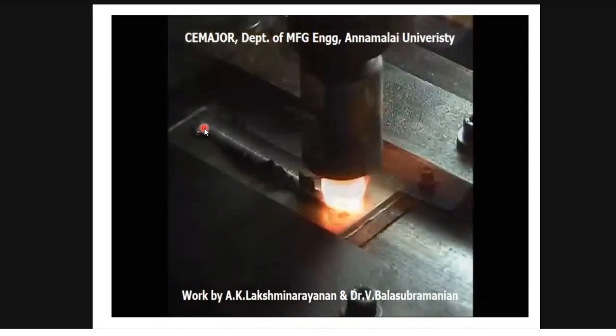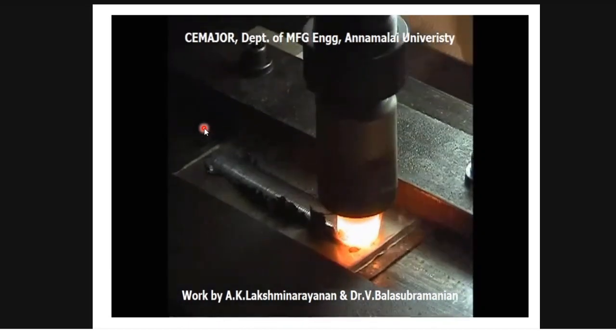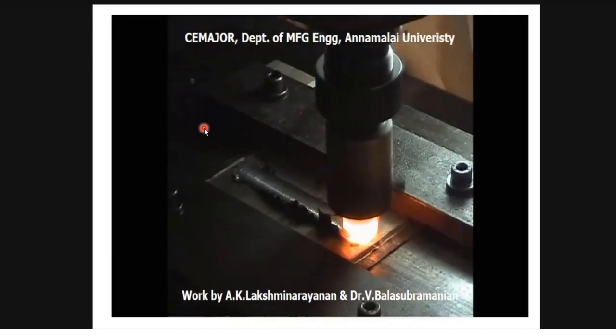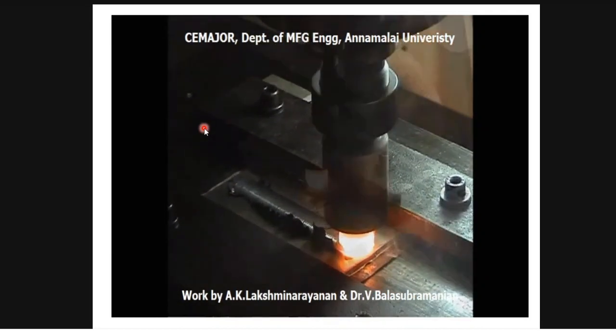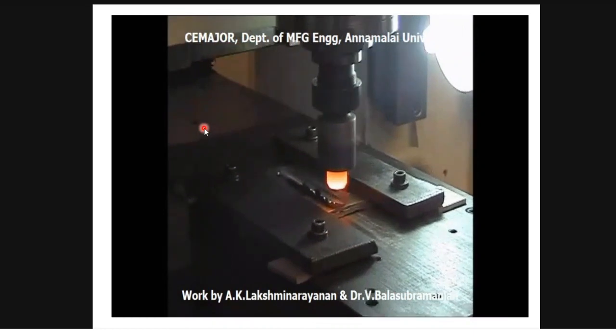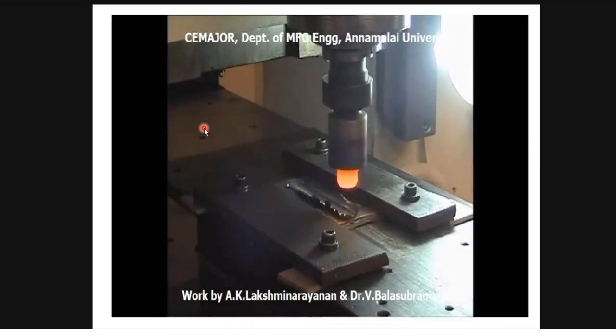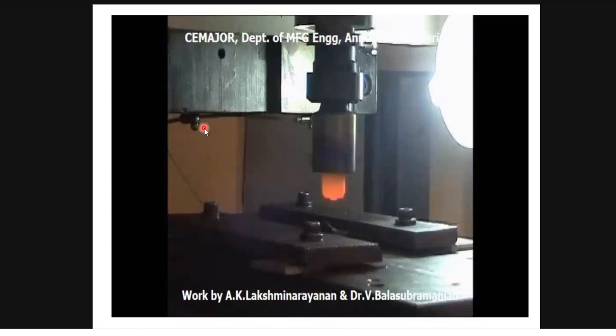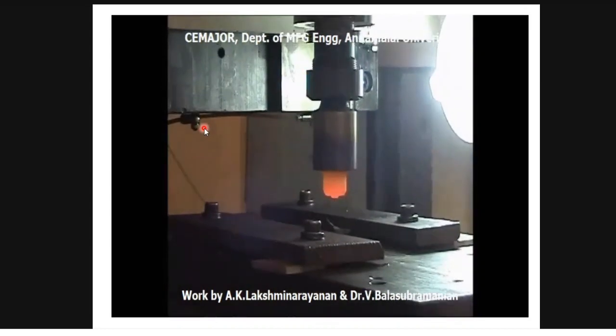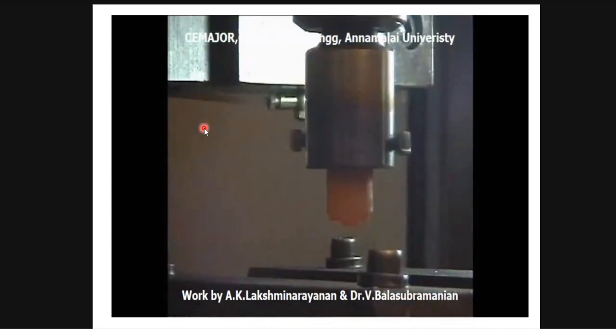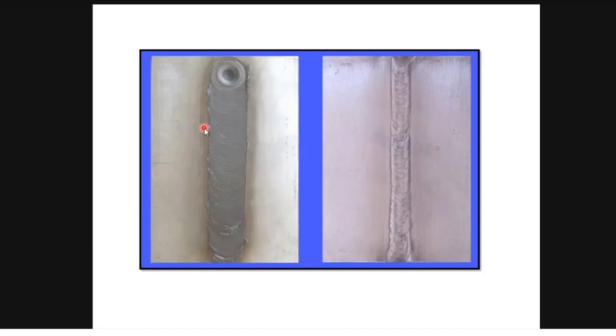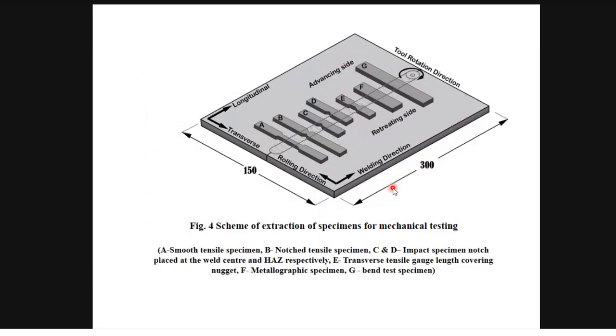So we started working on ferritic stainless steel because it has some problems while welding with the fusion welding process. Austenitic stainless steel is not a big problem for the fusion welding process, but ferritic stainless steel gives a lot of problems like grain coarsening, and many other problems. To overcome this, we went for the solid state welding process, FSW. So these are the joints. This is the FSW joint, and this is the GTAW joint, and they were compared.